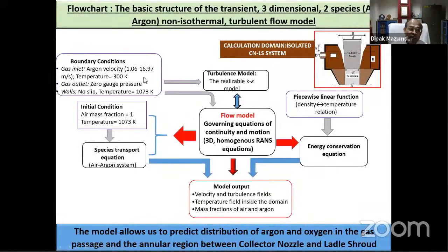So to understand the air-argon distribution in an actual shroud system, you have a collector nozzle, and we have a ladle shroud. There's a section of it which is shown here. Gas is being injected here, and we want to find out in this annular region what is the distribution of argon and air. We have developed a model also, because this water model result may not be exactly applicable, as the temperature effects etc. are not there. So we have a species conservation equation which considers two species in the system, air and argon. We have an energy conservation equation which takes into account the flow of gas in a hot shroud, because the shroud wall temperature could be something like 900 degrees centigrade.